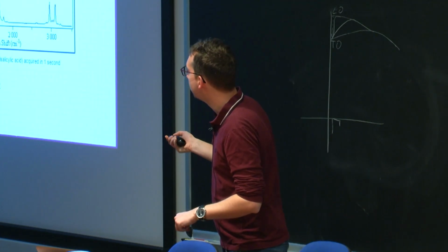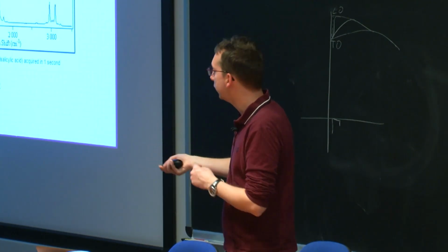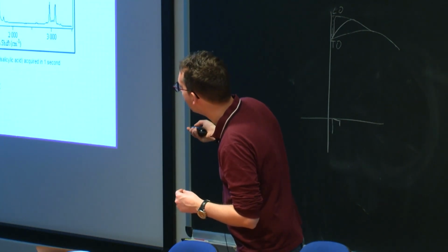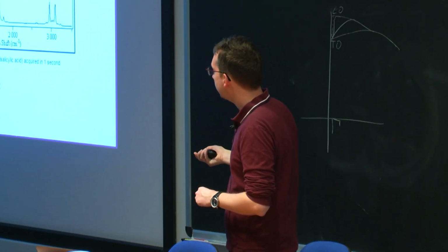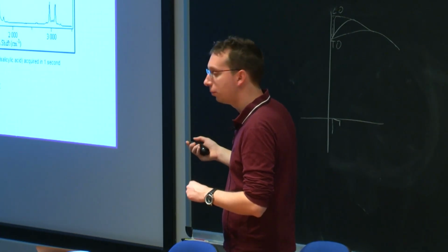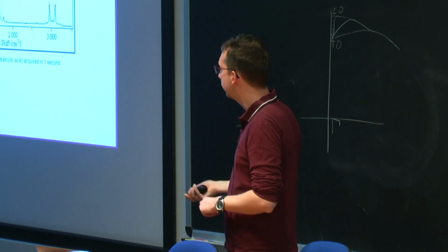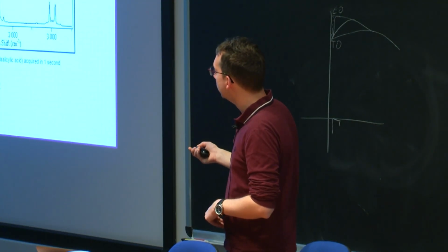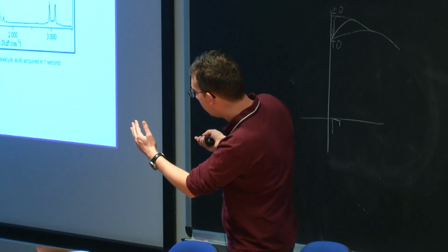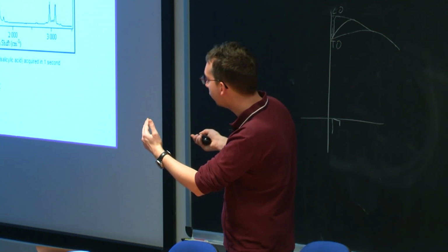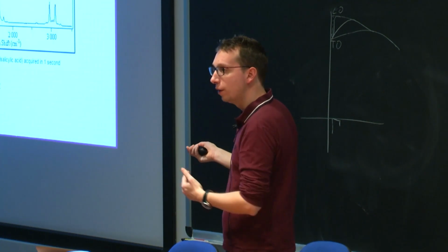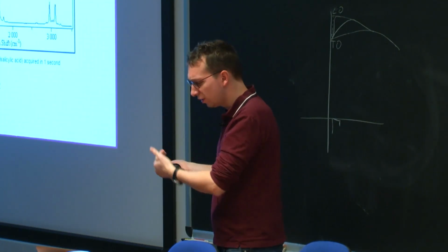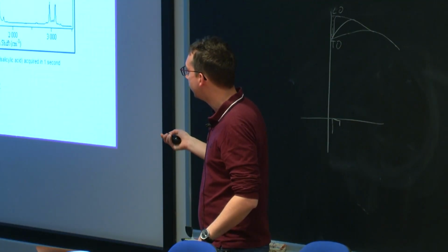And so at zero, which means the light goes in and comes out at the same wavelength, you have a big peak here. And then you have a certain number of peaks. It's important to notice that this elastic peak can be quite wide in some cases, especially if you have materials with heavy atoms, where the spectrum of the phonons is compressed toward the low energy because of the mass. Sometimes you get this elastic peak, which makes it a bit difficult to interpret the rest.